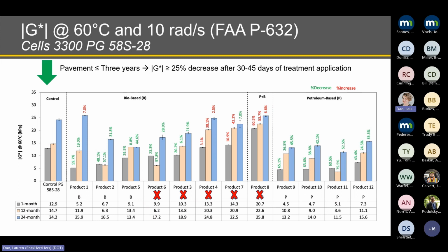Regarding the parameter used by the P632 specification, we have stiffness at 60 degrees Celsius and 10 radians per second. Per the FAA specification, if a pavement is less than or equal to 3 years old, for a product to be classified as effective, this stiffness needs to have a decrease of equal to or higher than 25% between the time interval of 30 and 45 days after the product is applied.